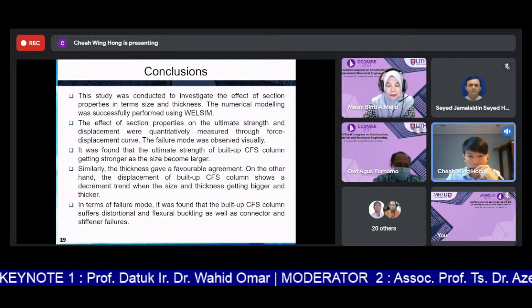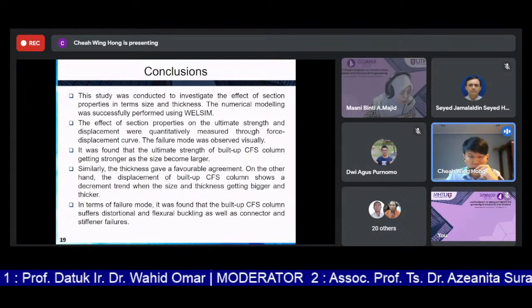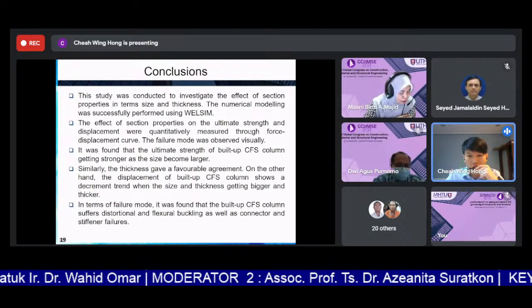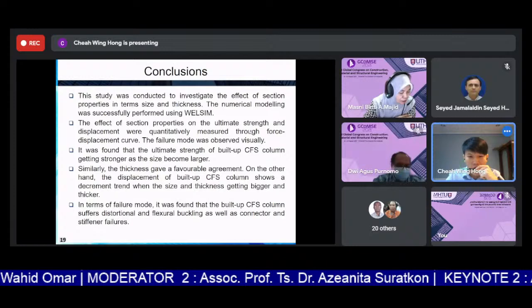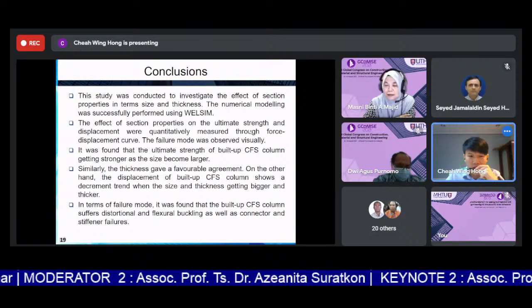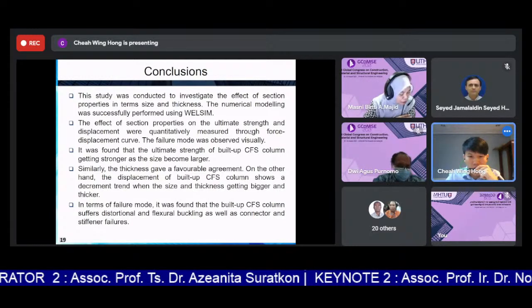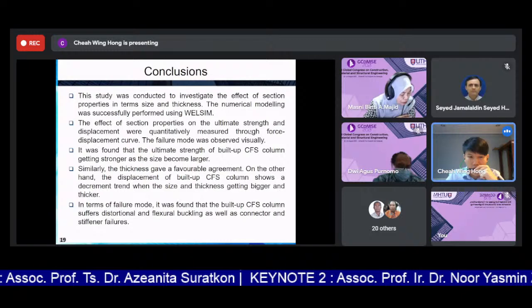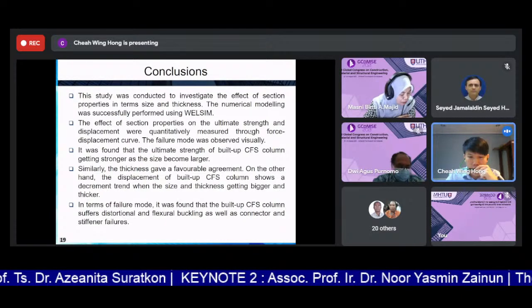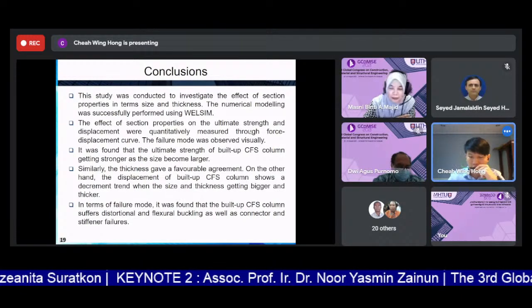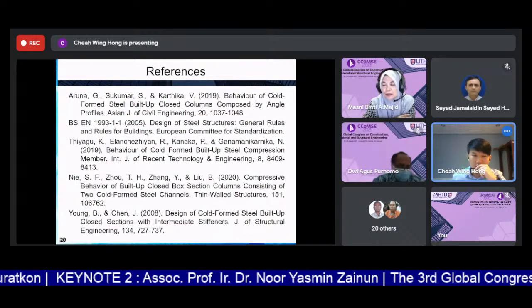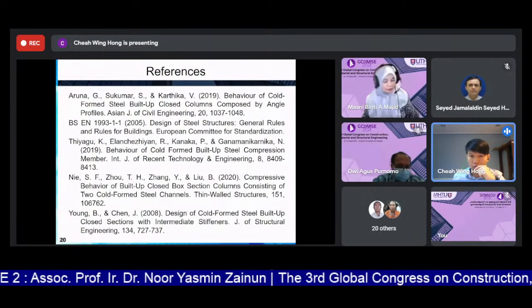On the other hand, the displacements of the built-up CFS column show a decrement trend when the size and thickness get bigger and thicker. So in terms of failure mode, it was found that the built-up CFS column suffers distortional and flexural buckling as well as connector and stiffener failures. So these are the references involved in this paper. And that's all from me. Thank you.